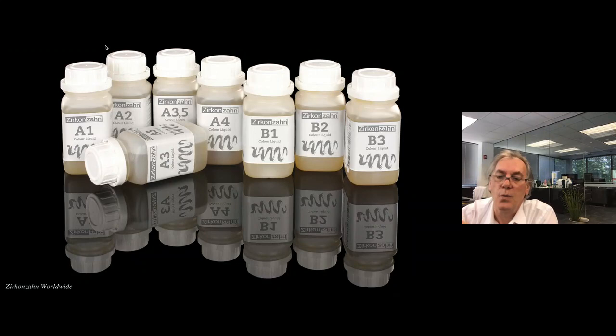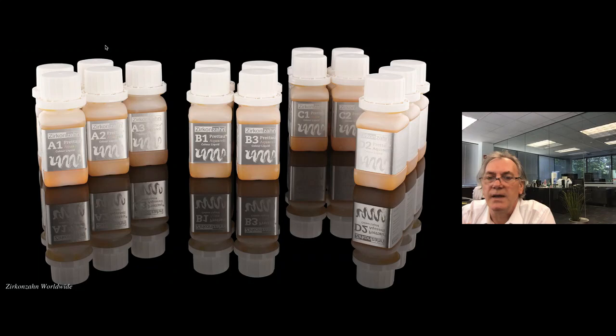The water base is a little bit easier to treat and to work with. It doesn't penetrate as much as the acid. It goes in around about three-tenths of a millimeter. The color effects are certainly amazing. But one of the major issues could be if there's only touchings to be done on the occlusal surface not being well infiltrated, we can encounter the risk that these little white dots pop up onto the crown and makes it really very difficult to eliminate.